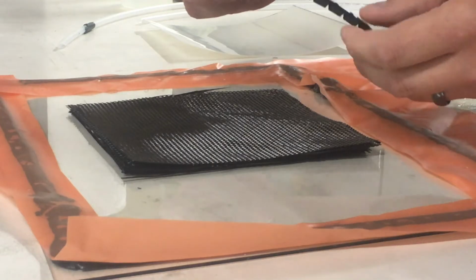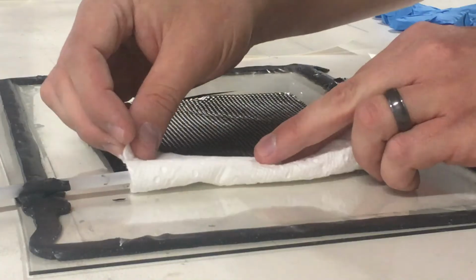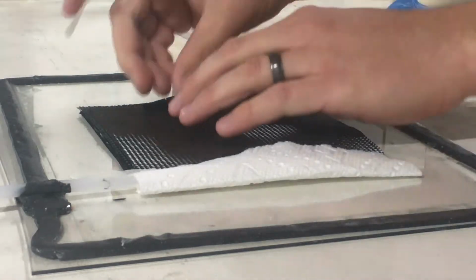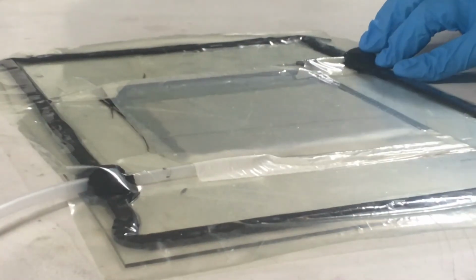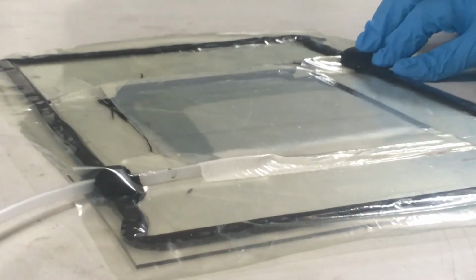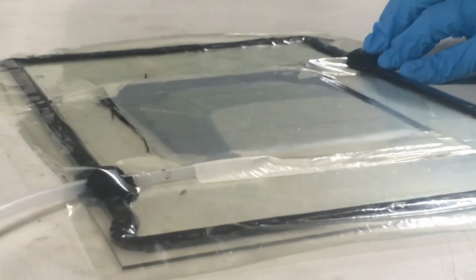Vacuum infusion is one of the best ways to get a really good surface finish on your part. The principle behind vacuum infusion is that you put all the plies in the mold dry. Then you have 2 ports inside the mold, one where you're pulling the vacuum, sucking all the air out, and then another port on the other side of the mold that lets the epoxy flow into the layup. So as you're sucking the air out, you're also sucking the epoxy in, and it flows from one side of the layup to the other, and you get a very low porosity part.